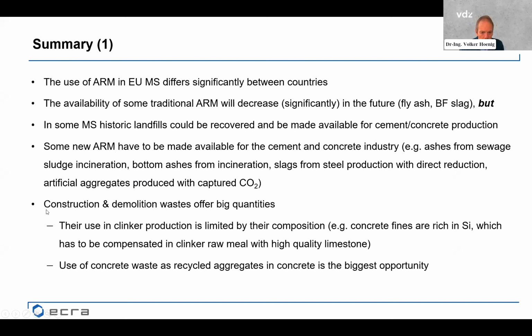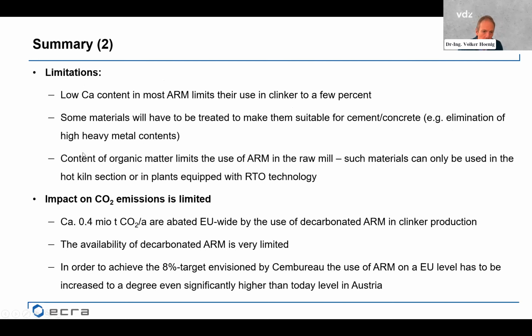Construction and demolition wastes also offer big quantities, but their use in clinker production is limited by their composition. For example, concrete fines are rich in silica, which has to be compensated in clinker raw meal with high quality limestone. And the use of concrete waste as recycled aggregates in concrete is the biggest opportunity. Regarding limitations, as I said, the low calcium content in most ARM limits their use in clinker to a few percent. Some materials will have to be treated to make them suitable for cement and concrete, for example, by elimination of high heavy metal contents, like in incinerator slags.